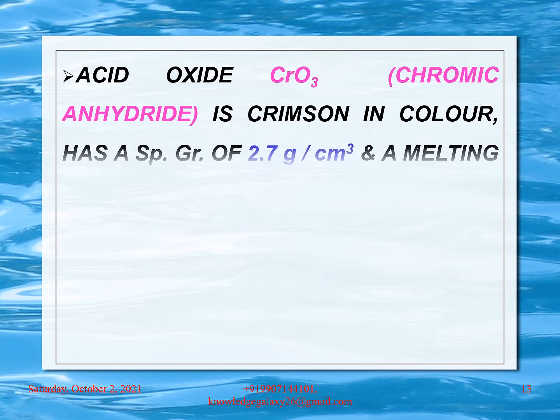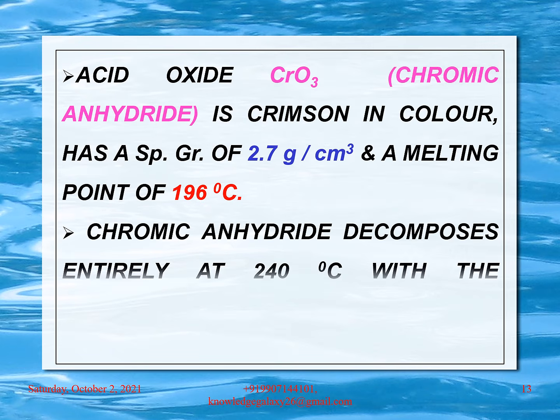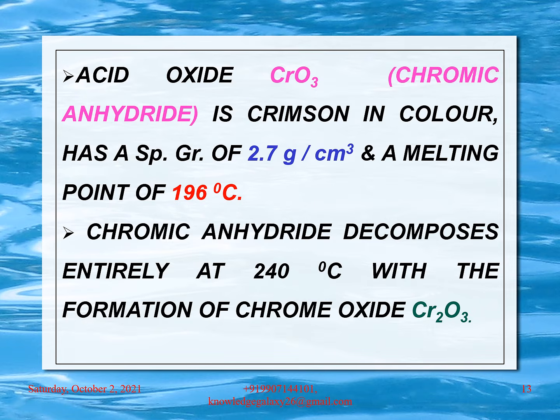Acid oxide CrO3, that is chromic anhydride, is crimson in color, has a specific gravity of 2.7 gram per cubic centimeter and a melting point of 196 degrees Celsius. Chromic anhydride decomposes entirely at 240 degrees Celsius with the formation of chrome oxide Cr2O3.